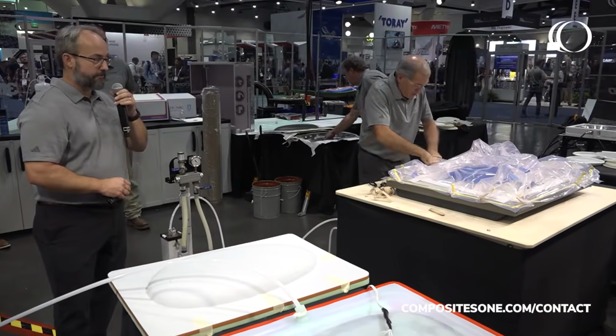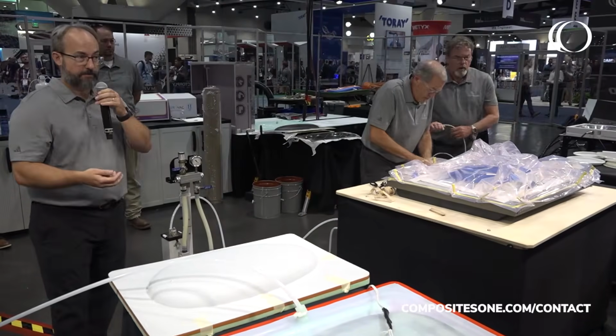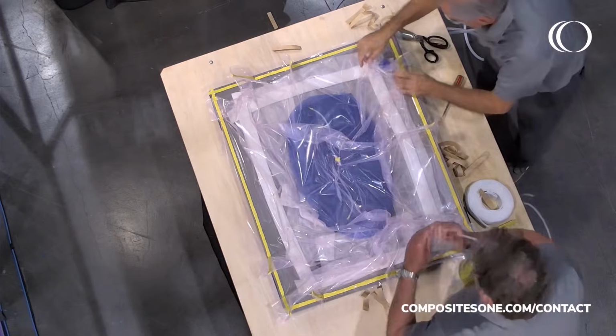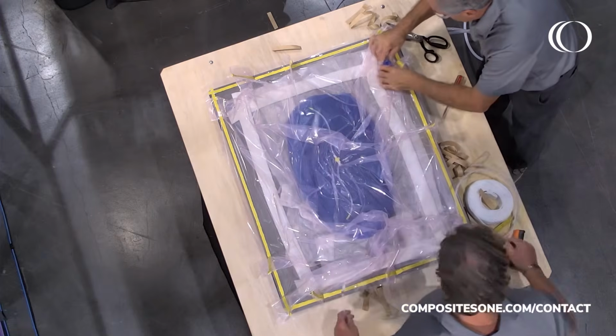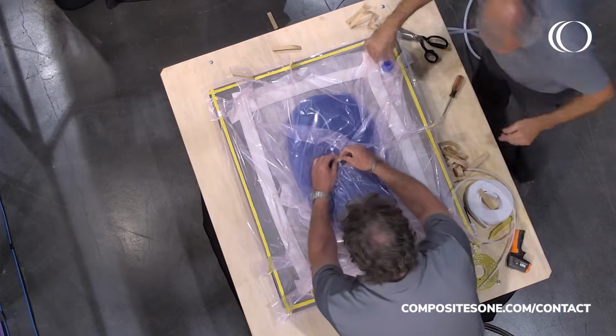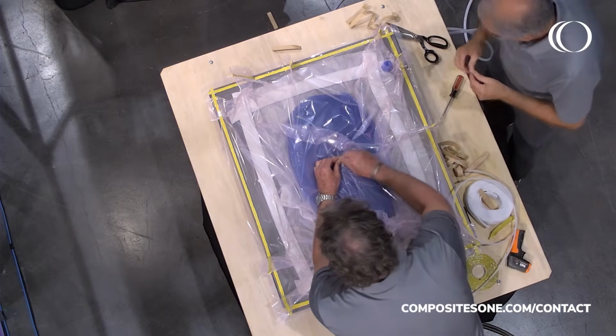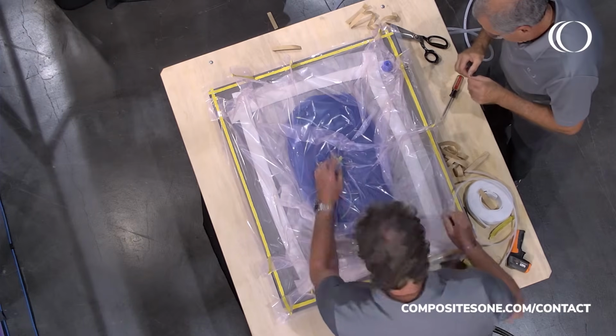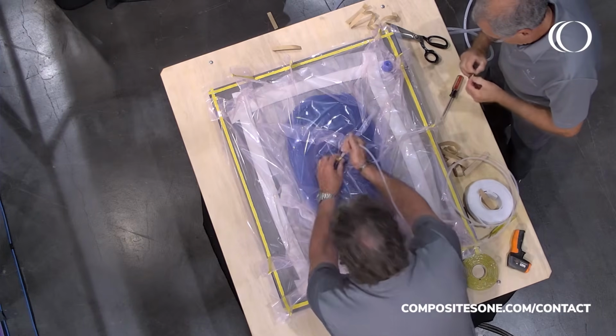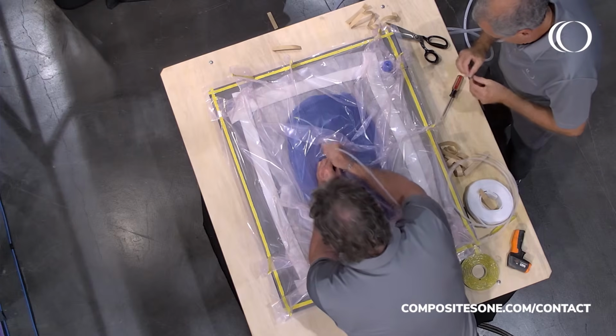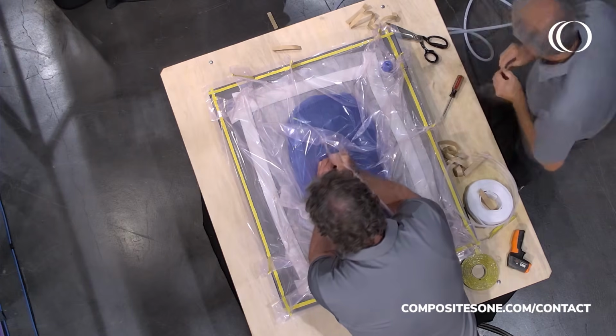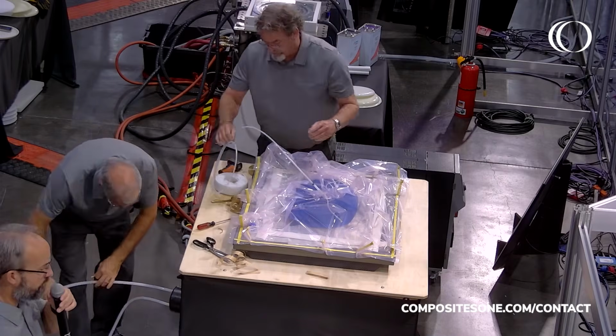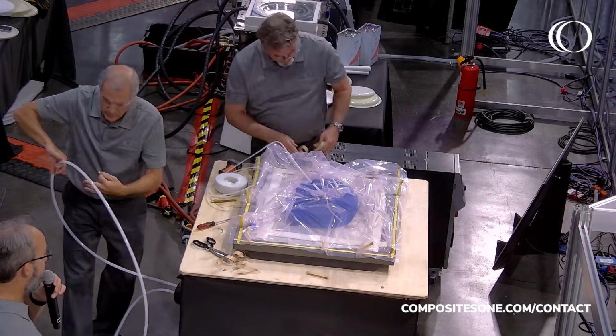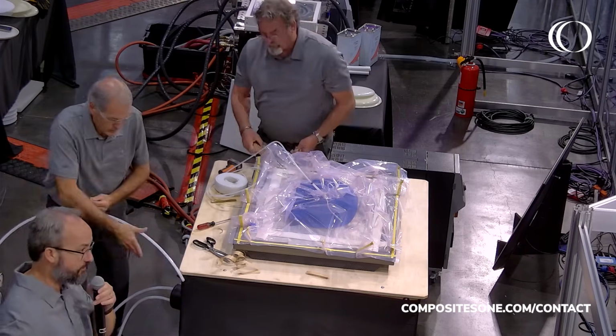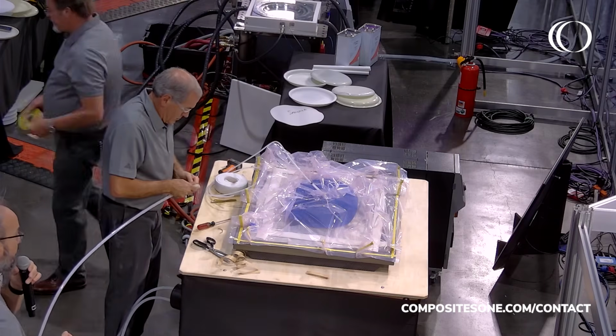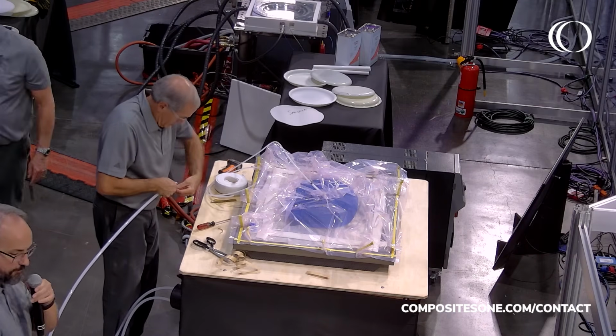Dan and Barry are putting pleats in the vacuum bag. The vacuum bag's oversized by about 20% to allow it to conform completely to the mold. The SV4000 material has very high elongation, but we don't want to rely on that elongation to get into the corners, because otherwise we could have bridging. If we have bridging in the corners, we're going to have resin-rich areas. In the process, they could cause high exotherm, and in the final part, it could lead to brittleness.